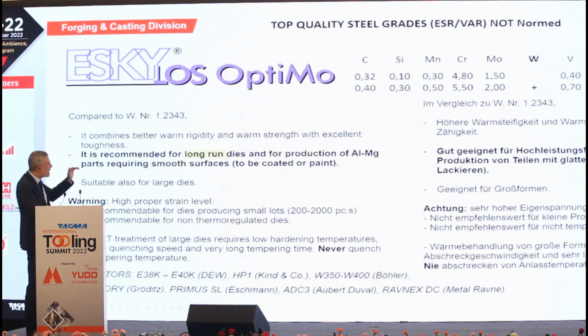Okay? Now our specialties. ESKYLOS OptiMo has been developed starting from 2343 with decreasing the content of silicon and adding some content of tungsten. Okay? Combines better warm rigidity and warm strength with excellent toughness if we compare it with 2343. It is recommended for long run dies and for production of aluminium magnesium parts requiring smooth surfaces to be coated or painted. Also suitable for large dies.